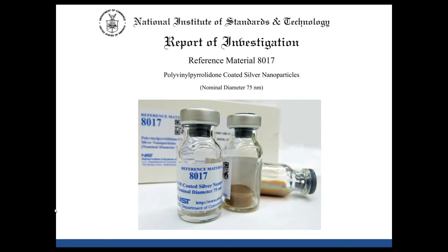So one of the ways that we got around that was for some materials we used silver nanoparticles that were in a dried format. Previously we had told people that drying components was not a good idea because the particles would be permanently aggregated. But we found a way to lyophilize them, and then you can just add water and they'll pop right back up and be in a non-aggregated state. This was used by NIST, which had this problem because they were required to provide a spec sheet that was absolutely reliable, but if they used liquid nanoparticles, they would change with time. So we'd start with this freeze-dried formulation, provide a ground zero after dissolution, and then things could be characterized after that.